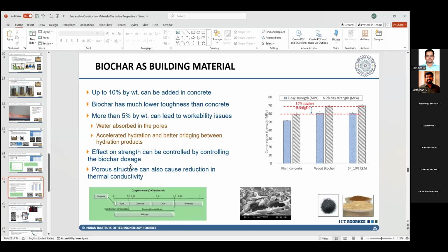Multiply that by another 2.2 times to get the carbon dioxide equivalent that you have stored inside your concrete for 1 cubic meter. And not only that, when you're doing so, you are able to increase your strength as shown here, because the internal curing effect of your biochar can help improve the hydration. Even though the biochar itself is weak, the additional hydration products that it generates can improve the strength.